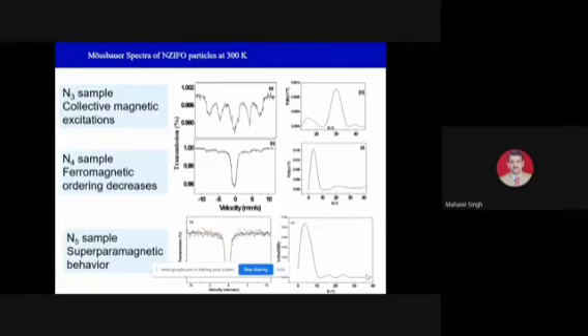Dear students, if there are new students or research scholars, you can correlate magnetic results with XRD. If you want to correlate XRD of bulk and XRD of nano, in nano the XRD pattern is broad, but in bulk the XRD pattern is sharp. So broadness means surface disorder. The same is the case in the Mossbauer distribution function which we also fitted. In nano we have a broad Mossbauer peak, but in bulk we have a sharp one. So broadening means surface disorder. When we move from bulk to nano, surface disorder increases. That is why there is broadening of the peak at nano level. Next, please.